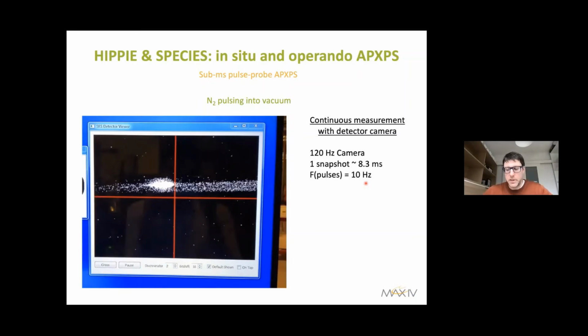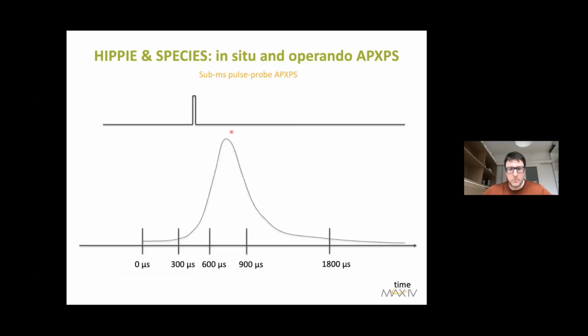How exactly do we do this measurement? Well, this is our pulse in time. We can measure it spanning from hundreds of microseconds to several milliseconds. Since the detector is synchronized to the pulse generation, we can measure a particular XP spectrum only in a short period of time. Then, varying the delay between the generation of a pulse and our probe, we can probe the chemical composition of both the gas phase and the surface at different delays as it evolves.